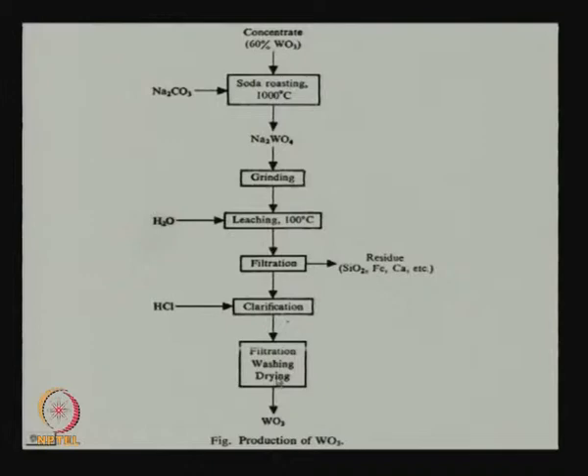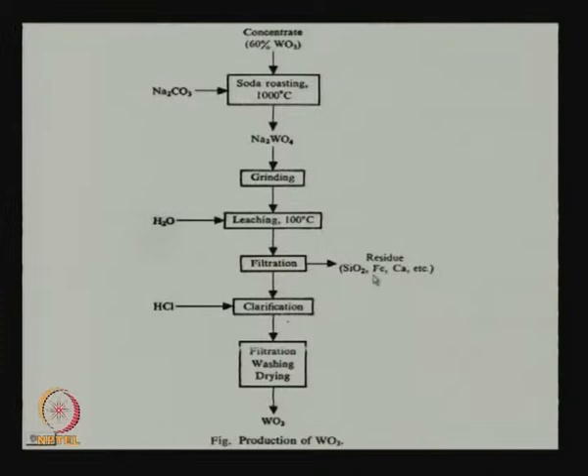Similarly, there are tungsten ores. Incidentally, India does have some tungsten ores in Rajasthan, at a place called Degana, but they are very low grade. Because tungsten is very heavy, using gravity separation we can get a concentrate going up to 60 percent WO₃. That goes for soda roasting — a standard procedure to produce Na₂WO₄. After grinding, water leaching, and filtration, we get a soluble tungsten compound. Treatment with hydrochloric acid precipitates WO₃. If you want pure tungsten, you start with WO₃.